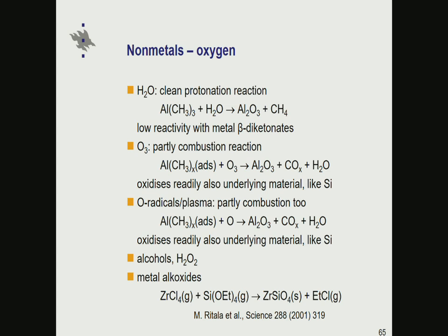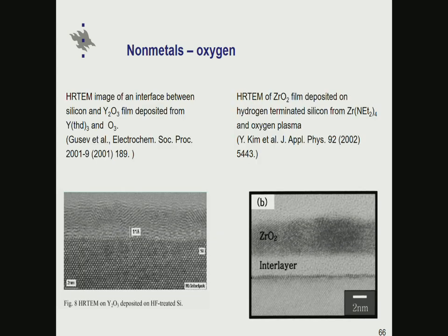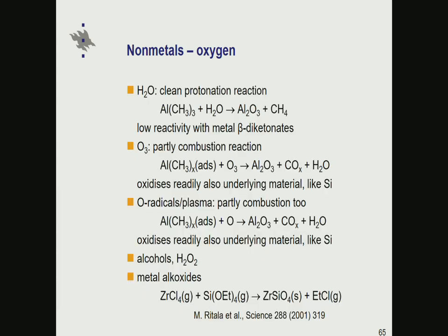What was also a limiting factor in taking these chemistries into high-K oxide deposition is that ozone is not only reacting with the metal precursor, but it's also reacting with the silicon surface when depositing these high-K oxides on silicon. This has been deposited using ozone. This has been deposited using oxygen plasma. In both cases, there is at least 10 angstrom of silicon oxide on the surface, and this is essentially a showstopper in using high-K oxide. This is too thick for the gate oxide stacks, and that's why there has been a need to use water-based processes for those.